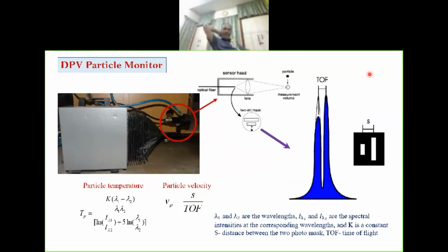For measuring temperature, what we do is detect the particle and sense the temperature of the particle at two wavelengths and measure their intensities. Once we get the intensities and the wavelengths, from a correlation, we can get the surface temperature of a particle.